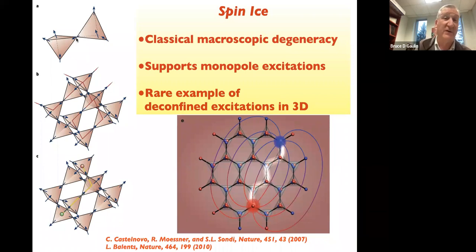They're classical magnetic dipole moments. I'm going to create a magnetic excitation here the only way I can, given what I've told you, which is to flip one of these spins. I'm going to flip the spin that's at the vertex that connects the two tetrahedra. And when I do that, I'll make one of the tetrahedra 3 spins in, 1 spin out, and the other one will be 1 spin in, 3 spins out. And so I'll have put defects on these 2 neighboring tetrahedra.